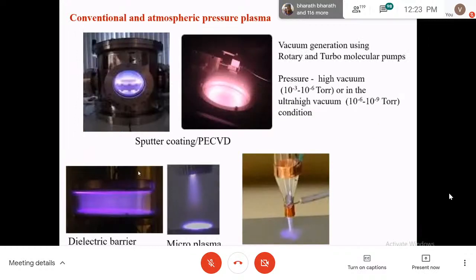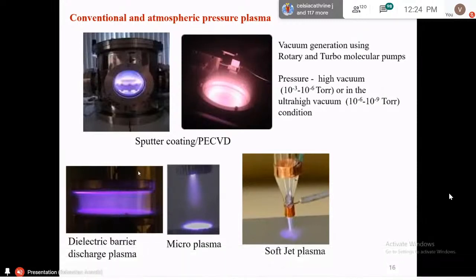Conventional plasma systems usually utilize very high vacuum. We have to create a vacuum in the range of 10 power minus 3 to 10 power minus 6 torr, and beyond that it is called ultra high vacuum, in the range of 10 power minus 6 to 10 power minus 9 torr. We have to utilize rotary and turbo molecular pumps to create the vacuum. Whereas in atmospheric pressure plasma, we do not use any vacuum generation equipment. It is just operated in the normal atmosphere.